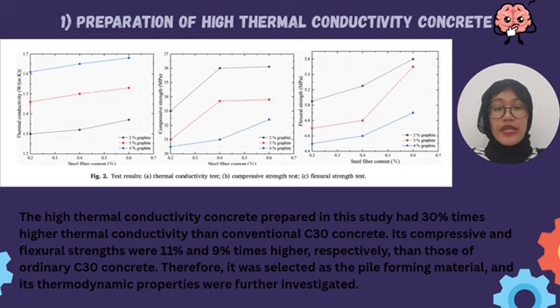The third graph presents the flexural strength test. Similar to the other results, both graphite and steel fiber contribute to better performance. The combination of higher percentages leads to the strongest outcome. Overall, the concrete prepared in this study achieved 30% higher thermal conductivity compared to conventional C30 concrete. In addition, the compressive strength was 11% higher and flexural strength was 9% higher. Because of these improved mechanical and thermal properties, this special concrete was chosen as the pile-forming material for further investigation in our model test.